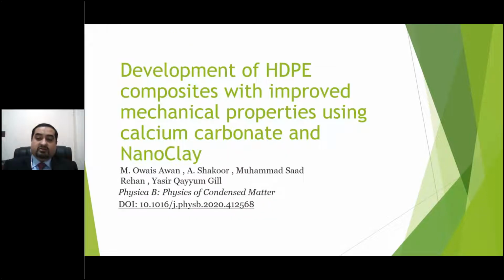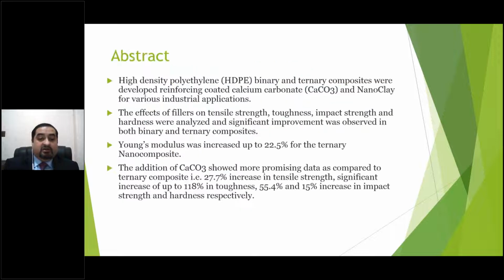Now, in another research carried out in this field was the development of HDPE composite with improved mechanical properties using calcium carbonate and nanoclay. In this research, we utilized calcium carbonate and nanoclay to reinforce our materials. The effect of fillers on tensile strength, toughness, impact strength, and other properties was studied, and we found that Young's modulus was increased up to 22.5% for the ternary nanocomposite that we developed in the combination of calcium carbonate and nanoclay and HDPE.